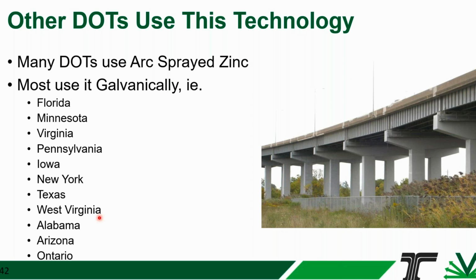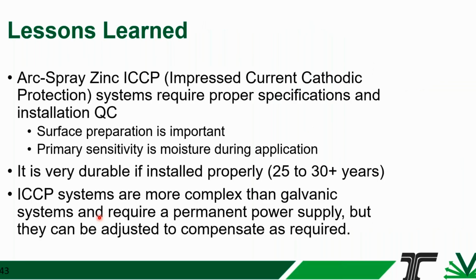In terms of lessons learned, surface preparation is really important, and in terms of QC, surface preparation and making sure that the surface is dry enough and the application environment is dry enough are probably two of the most important things. If the zinc is installed properly, it's very durable. This system lasted between 25 and 30 years, and Ray may comment on this later, but he and I share the view that if they ran the system a little bit differently than they did, it would last well over 30 years.